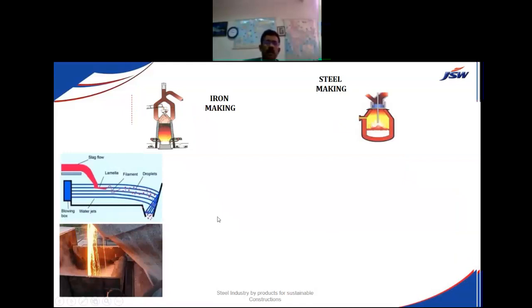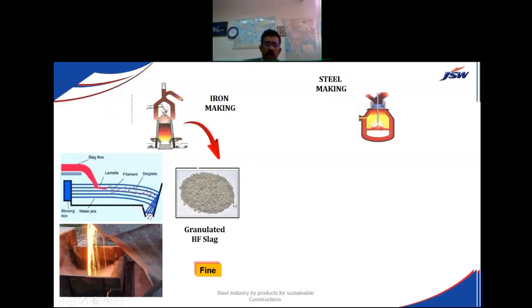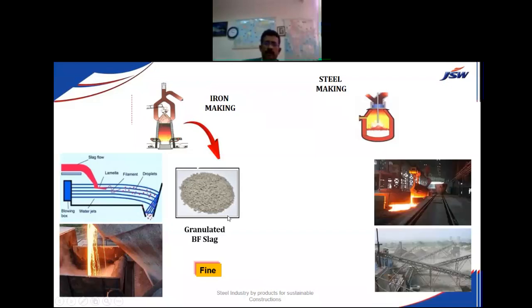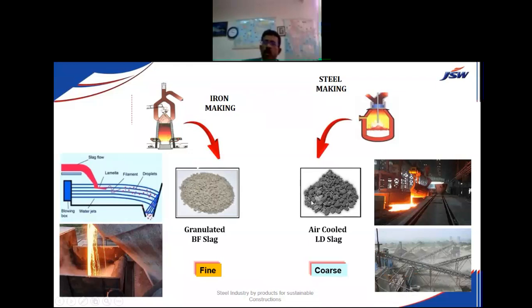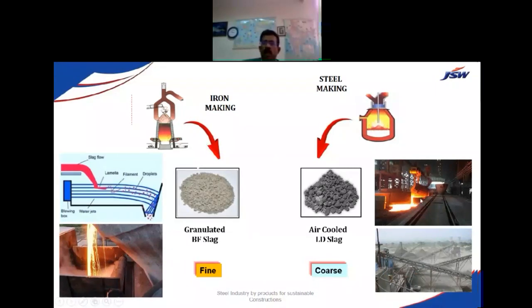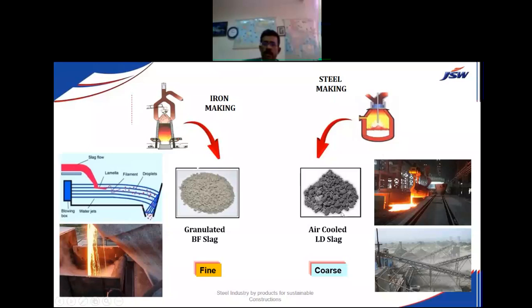So how do we convert it into a useful product? When the slag comes out, we have a separate setup through which it flows, and we put water jets and a blowing box. With that it gets converted to small granules, which become granulated blast furnace slag, used for fine aggregates. When we do air cooling, which we don't do in the same way for steel making, we get air cooled LD slag, which is a little bit darker in nature. We make coarse aggregates from this.